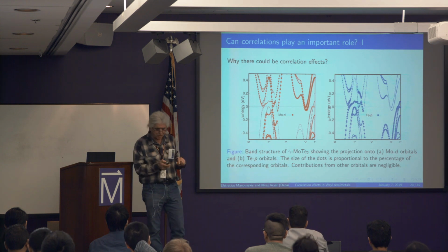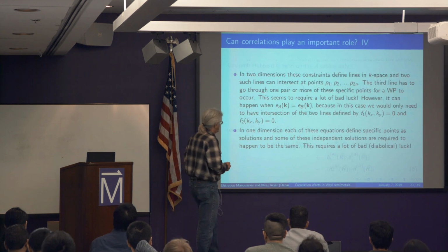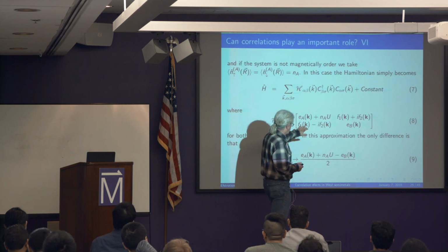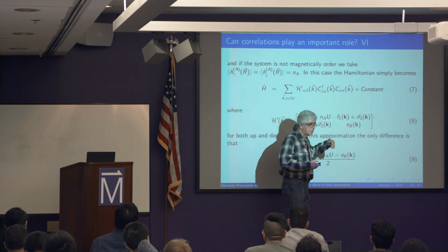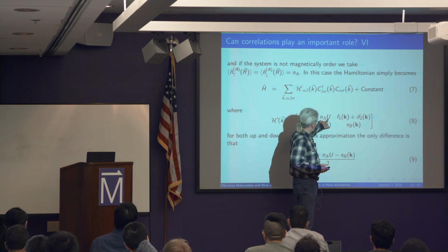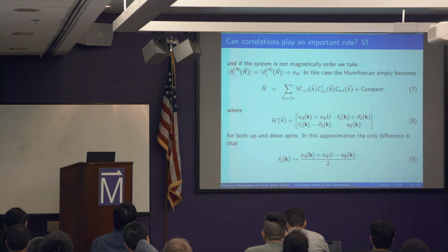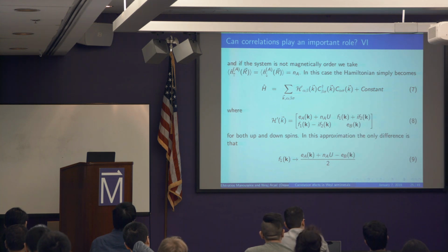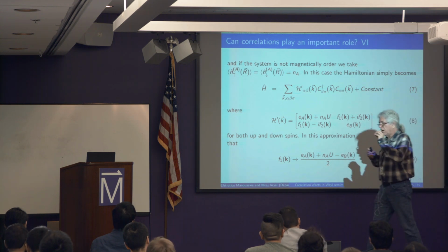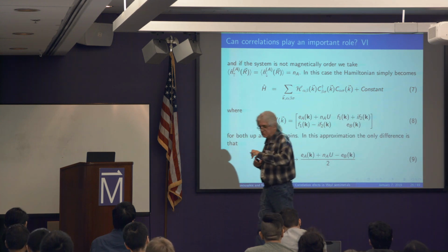So the two are together; what comes in this matrix is the product. So even though this is small, if the U is 2 eV, you'll get 50 milli-eV, no problem. Nobody will question it if you use 2 eV as a U on the d orbital.